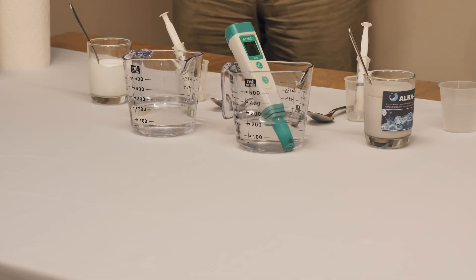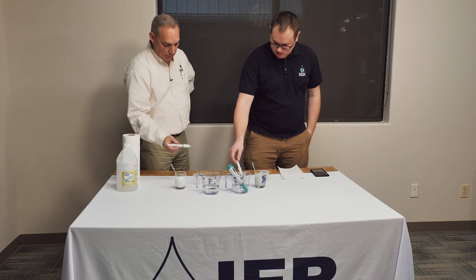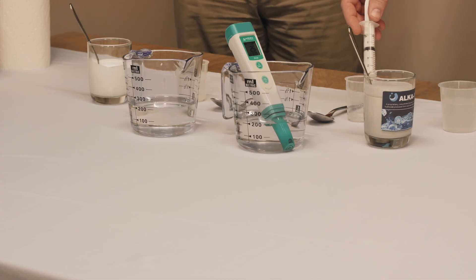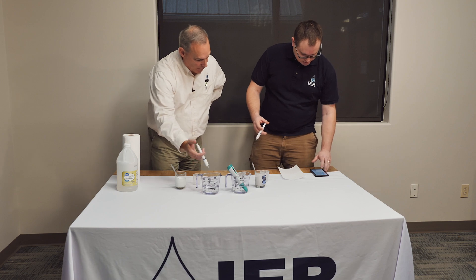We're going to add 6 mL of each magnesium hydroxide and let it run for 30 to 45 minutes, taking the pH every one to two minutes at the beginning and then around five-minute increments as we get further along. From that pH data we're going to get a story of the difference in reactivities between the two products. Let me get the timer ready to go, Doug, and we can get started.